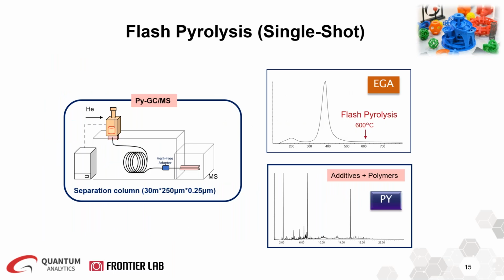So this is the flash pyrolysis, or single-shot GCMS. As shown here, the EGA was first obtained to identify the optimal pyrolysis temperature, in this case 600 C. To perform the flash pyrolysis, the EGA tube is then switched to a separation column using the GCMS vent-free adapter.